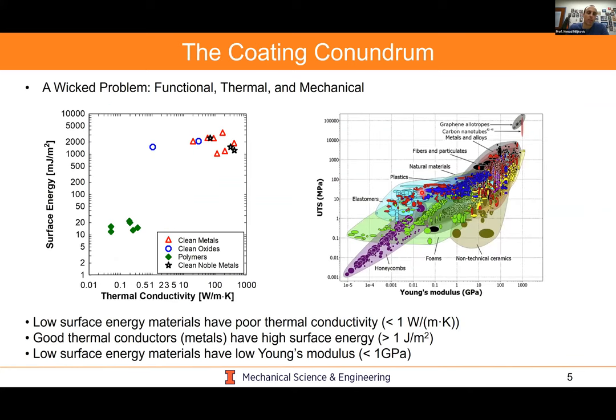So fundamentally, when discussing those issues of durability and coating thinness, I call it the coating conundrum, but in reality, it's a really hard challenge, mainly from the perspective that if we were to look at the intrinsic material properties of common materials, and if we were to plot something like the surface energy as a function of the thermal conductivity of the material, we see that what we want is a high thermal conductivity for thermal applications. But at the same time, we typically want a very low surface energy for phase change heat transfer applications. And in reality, these two are mismatched because the majority of materials which have high thermal conductivity, like clean metals, metal oxides, ceramics, semiconductors, they typically have a very high surface energy, and water or other refrigerants will wet them spontaneously. Meanwhile, where we really want to be, we actually want to have low surface energy like polymers, but the majority of polymers actually have very low thermal conductivity.